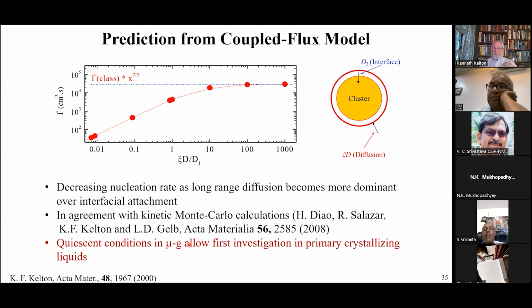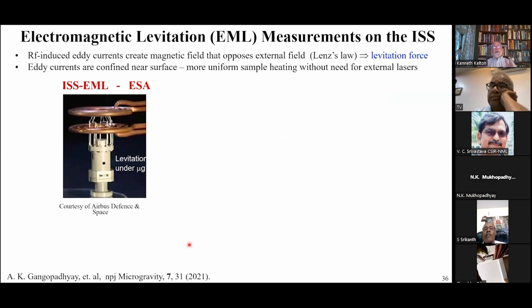And so the quiescent conditions in microgravity allowed this to be checked. This is an example of the ISS EML on the European Space Agency. What is EML? It's electromagnetic levitation. Here, what you do is you have an RF coil, RF field that creates a magnetic field in the sample that's levitating between the coil, and that in turn creates eddy currents in the sample, which creates an opposing magnetic field, and so it levitates.